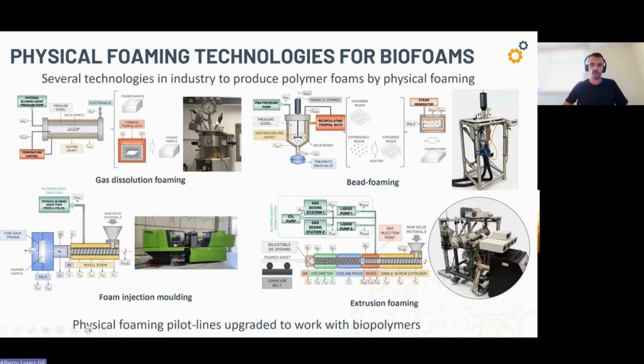And we have more foaming pilot lines based on physical foaming, which are very promising for the development of bio-based foams, because we don't use chemical blowing agents. We just use a physical foaming agent, which is not present in the polymer after the foaming process. And all these physical foaming pilot lines have been upgraded to work with bio-based formulations and biopolymers: gas dissolution foaming, supercritical foaming, bead foaming, the one we have been talking about, extrusion foaming, as well. We have 2 lines now, and also foam injection molding.